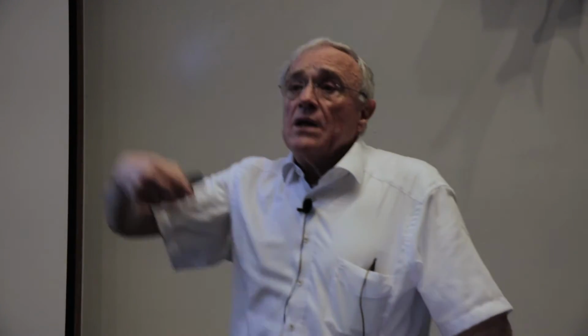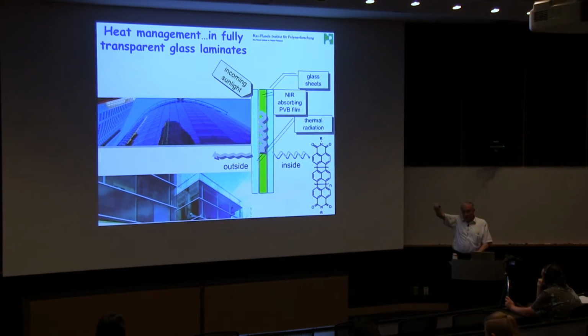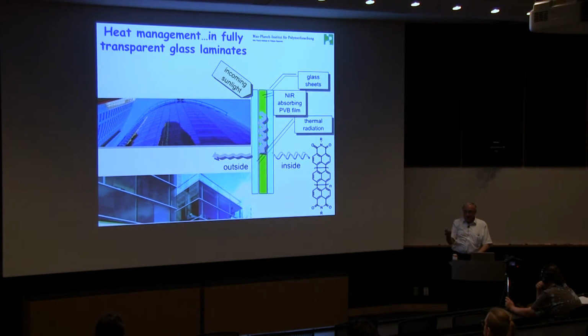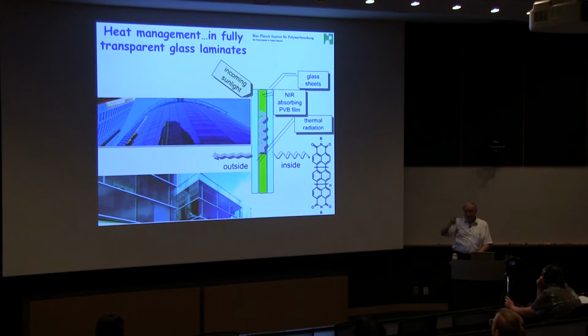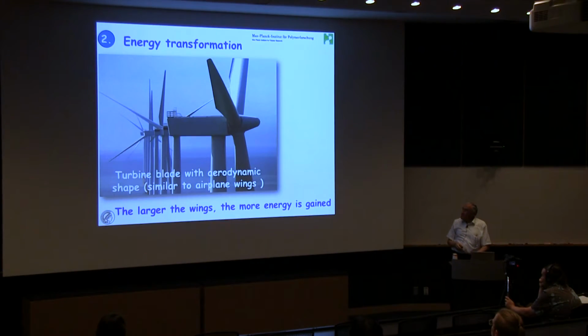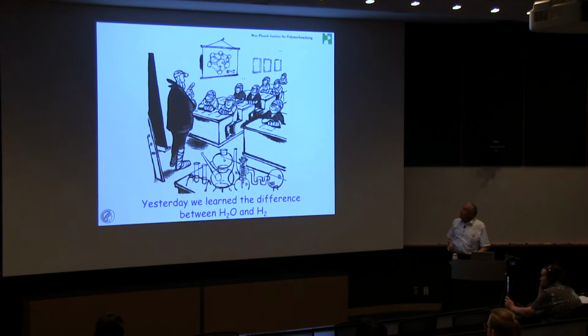I don't say, yeah, you anyhow produce heat, but you have much ventilation outside. So that's an efficient way of heat management, and it's cheap. It's a nice business, I can tell you. But you need the right absorption characteristics, and you need ultra-high stability. 8 years Arizona conditions and less than 3% loss of the absorption intensity. This is what I told you. When we talk about energy transformation, you would not be able to build such a turbine without carbon nanofibers.